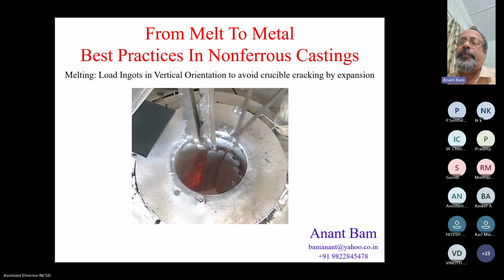While starting the melting in the empty crucible, one has to take care that ingots are placed vertically and loosely packed, not closely packed, because before melting, the ingots expand. There is thermal expansion of aluminum. If the ingots are not loosely packed, that expansion adds one onto the other, and it leads to cracking of the crucible by thermal expansion. So ensure that the ingots are stacked vertically and loosely packed.